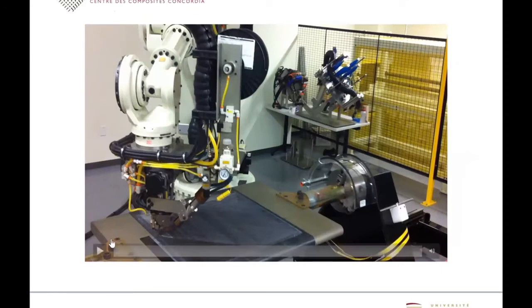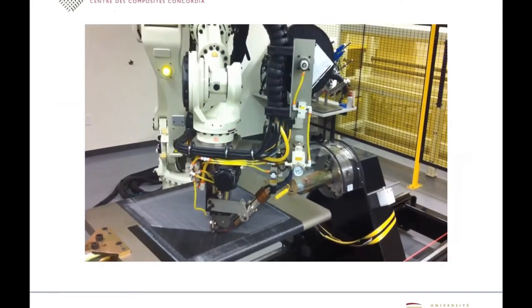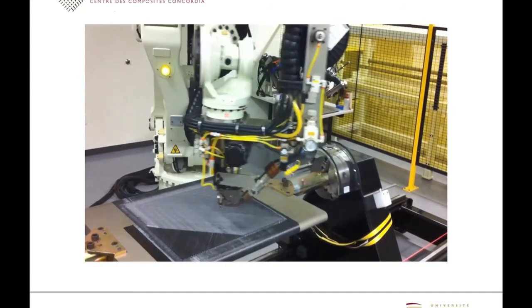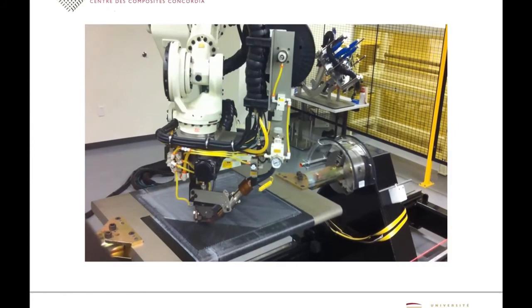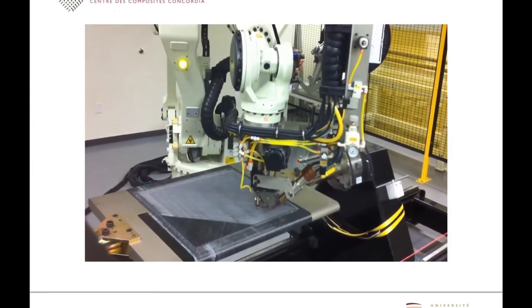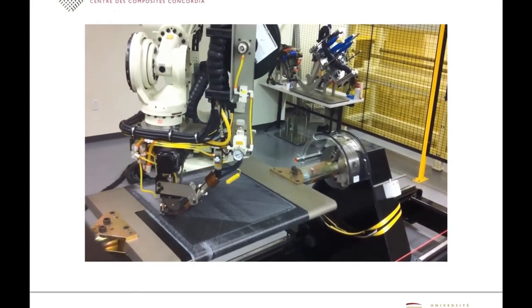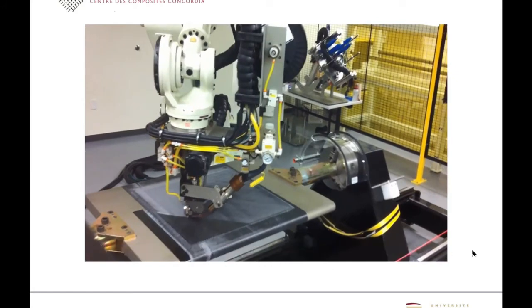So the next thing here, just to give you an idea what is meant by an automatic fiber placement machine. This one here, I'll show you a machine. Basically, it has a lot of complex things here, but it lays down some kind of a thermoplastic tape. And you can see that we lay that on some kind of a flat mandrel here. Right now we have the fiber along the 0 degree orientation. And what I show you right now is that the machine will lay down the fiber at 45 degree orientation. Okay, so that's basically the operation of the fiber placement machine. By controlling the machine, you can lay down the fiber at different orientations. And in this particular presentation today, we only look into the case where you have the 0 and 90 orientation of the fiber.